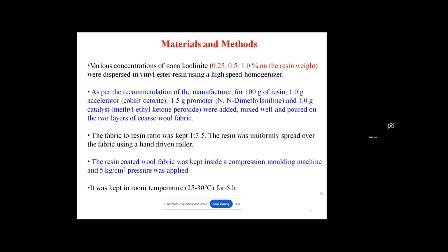We have taken nano kaolinite in different concentrations: 0.25%, 0.5% and 1%. The vinyl ester resin was taken in a 1:3.5 ratio with respect to the wool fabric. Initially we coated the wool fabric with the resin, and afterwards we compressed it in a compression molding or hot press machine at 5 kilogram per centimeter square pressure. Then it was cured at room temperature for 6 hours.